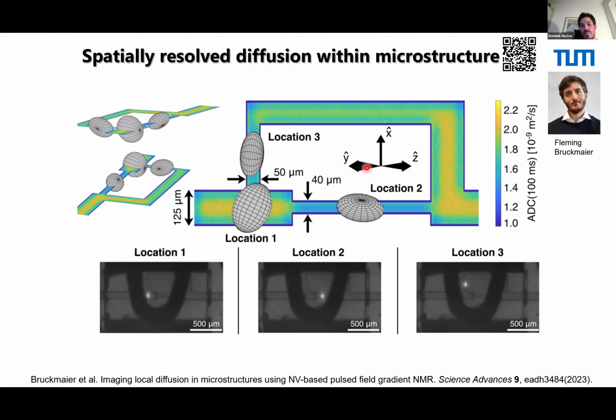And since we can do this in all 3 dimensions, X, Y, and Z, we get these ellipsoids here. Basically, it shows you, for example, let's go to the narrow channel here. We have limited diffusion confinement, a high diffusion coefficient in the Z direction, but a limited one in the X direction. And similarly here, it's less confined in the X direction, but more confined in the Z and the Y direction. And this, of course, you see we can do for different spots. You see it here in 3 dimensions a little bit more. Of course, there are some deviations. It's experimental data, but this is now a technique where we can make spatially resolved measurements at specific locations.